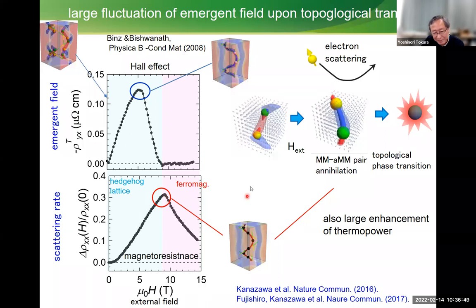So in this point, the monopole, anti-monopole pair should undergo a kind of pair annihilation. But near the some emergent magnetic field, some fluctuation, it's almost a continuous transition. So this kind of topological transition shows a very large fluctuation of the emergent magnetic field, which effectively scatters the electrons. We believe that this kind of large magnetoresistance is due to the large fluctuation of the emergent fields upon this topological to non-topological transition. Okay.